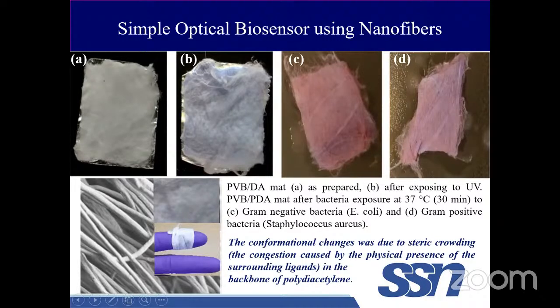Okay, and they exposed these nanofibers to both gram-positive and gram-negative bacteria. As you can clearly see, these nanofibers turn pink when exposed to gram-positive and gram-negative bacteria. This is due to the steric crowding that happens in the surrounding ligands at the backbones of PDA. Due to this, there is an optical color change, which gives you a simple optical biosensor, right?